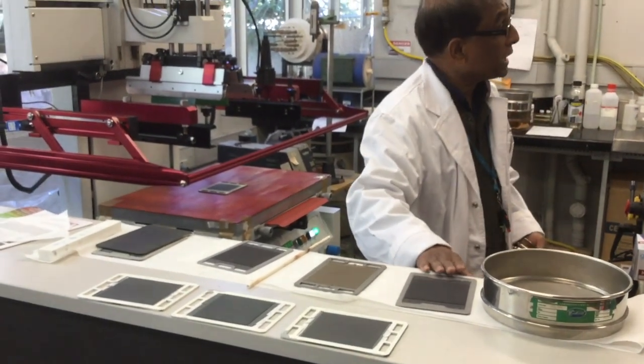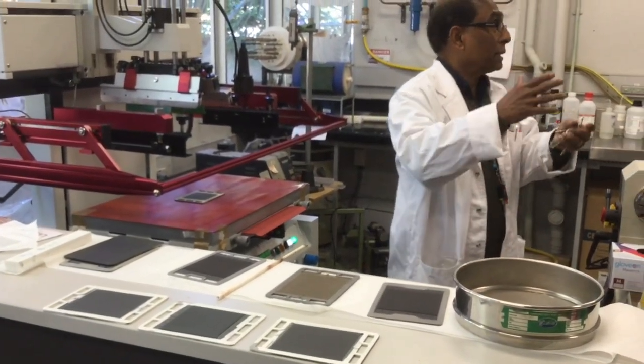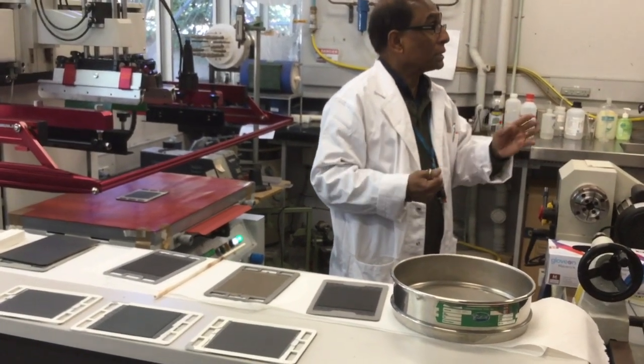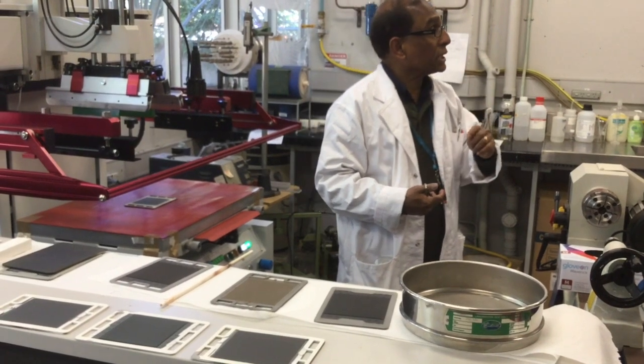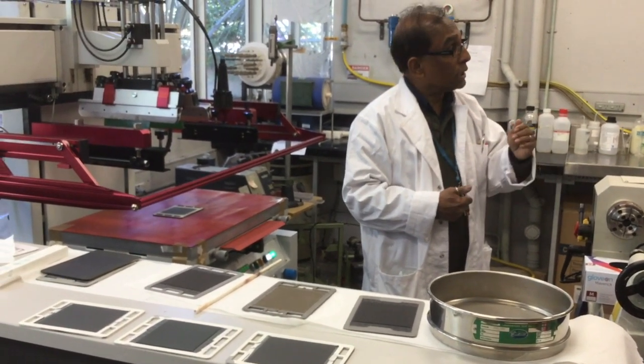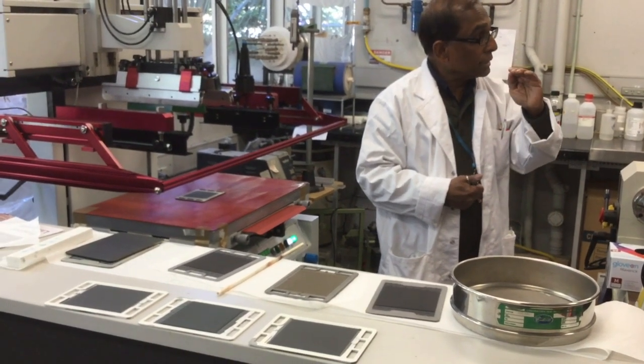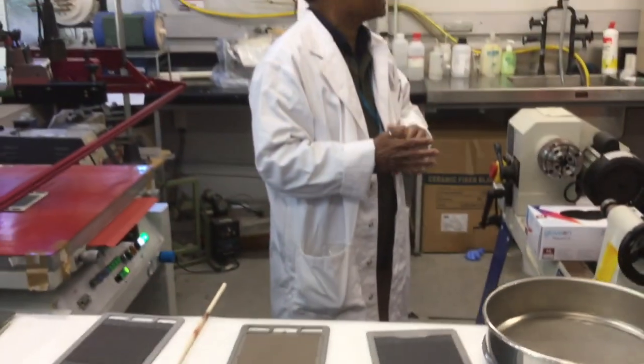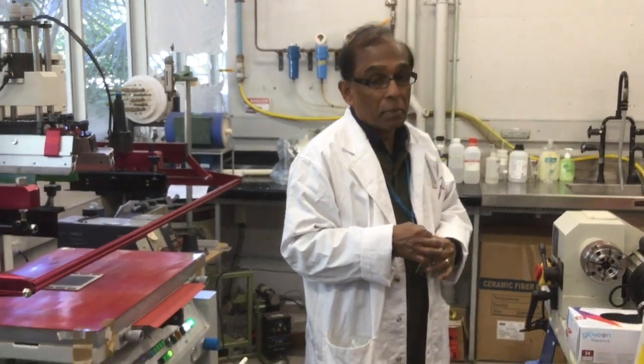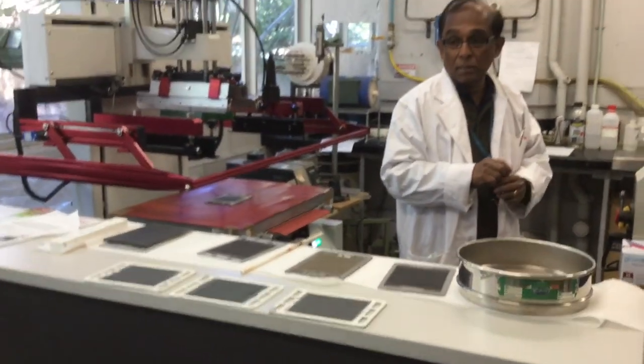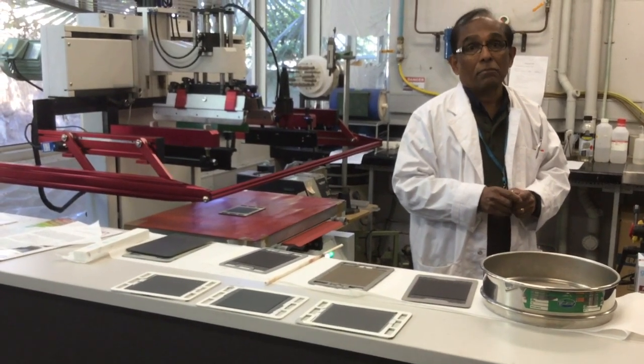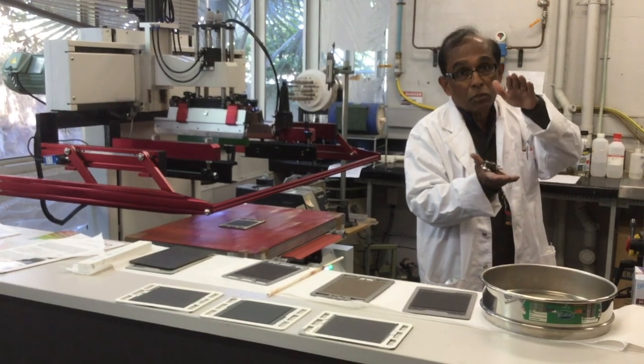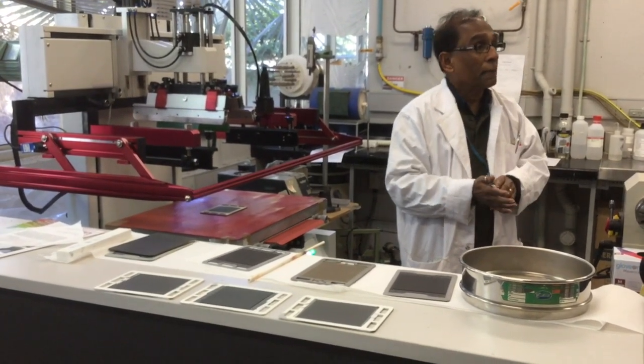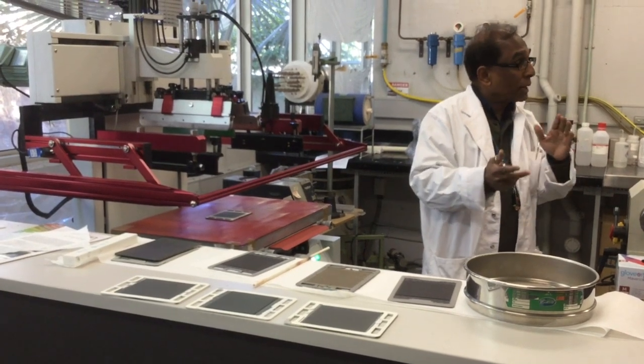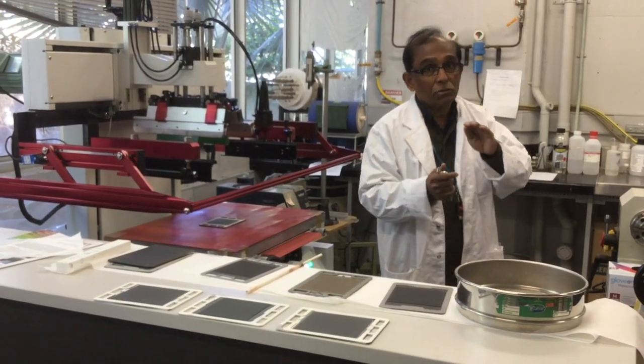But the coating that goes on this is heated when we put the stack together. So it has got a higher conductivity, and the current collection is more efficient. And because it has got the non-degradation additive in it, that coating does not degrade because of chromium poisoning, if any chromium is present. There are about 2 coatings I have to put down on each one of them. That stops degradation on the anode and cathode. And for compliance, when you put it together, there is a slight compliance in there at all times so that the cell doesn't break in the process. It's like a shock absorber.